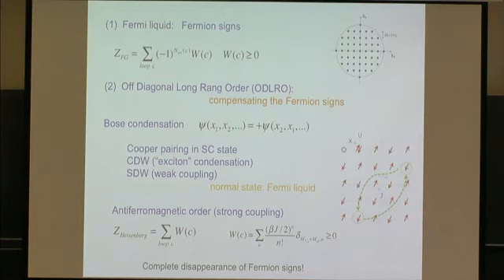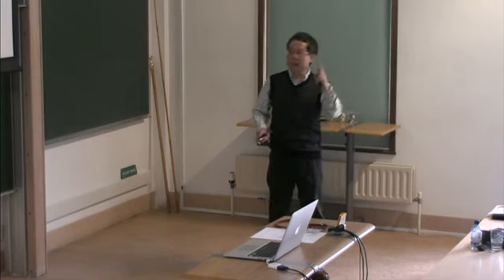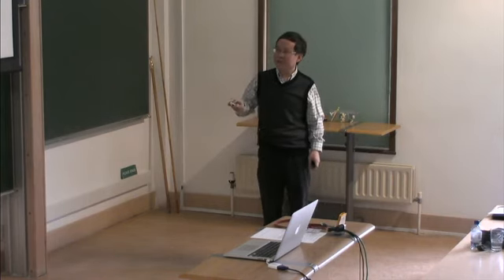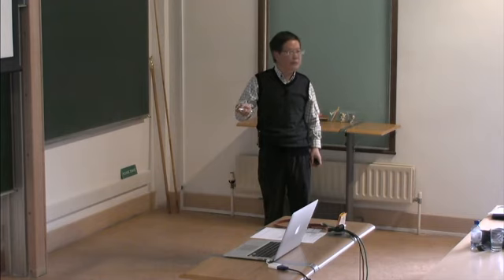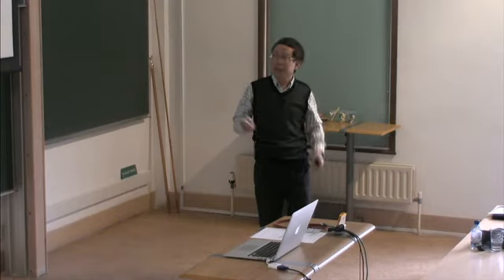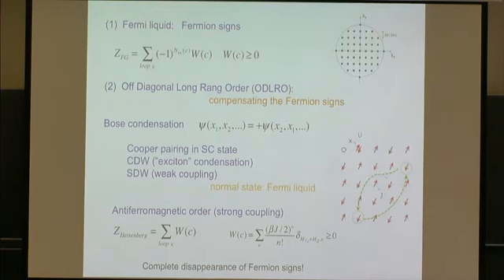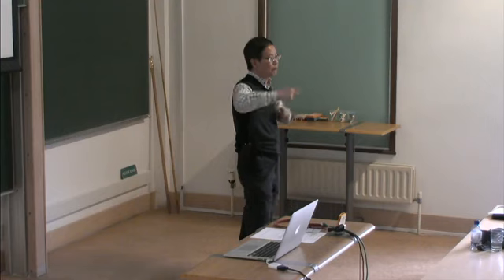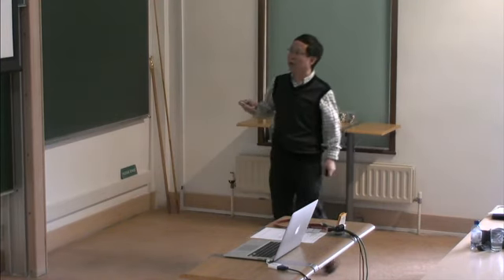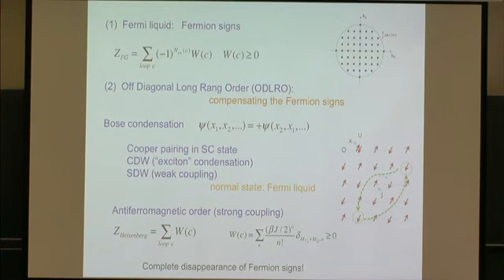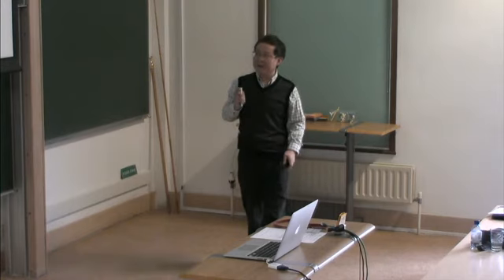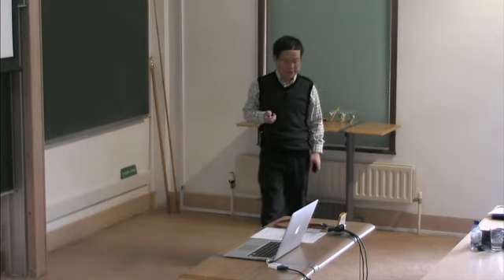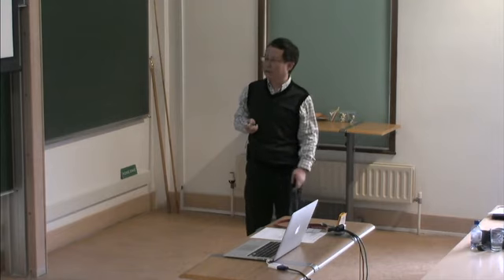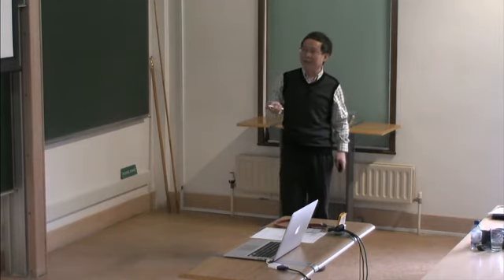In fact, the fermions are still fermions; if you switch two identical particles, they still change sign. But the issue here is that this process will not enter into a real physical process because the Hilbert space is changed. You don't allow double occupancy. So you cannot simply exchange these two particles in a real physical process. The physically allowed process is just to switch these labeled antiferromagnetic spins. So that's the essence of how the interaction changes the fermion signs in the half filling limit.